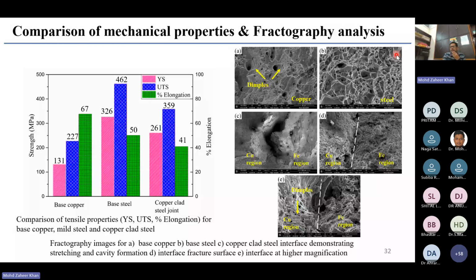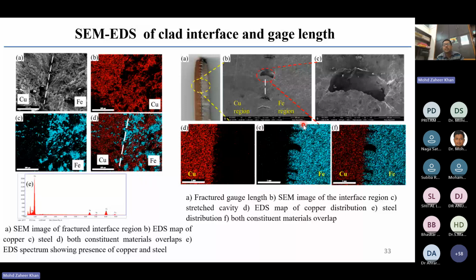These are the fractographs where you can see there are clear dimples present, and these two regions have remained intact even up to the point of the fracture. Whenever the fracture is taking place, these two regions are not getting separated. This is more visible in this magnified image of the tensile test specimen. As you can see, the specimen is fractured at this point, but when elongation or yielding is taking place, the two different materials are yielding together, but they are not separating out.